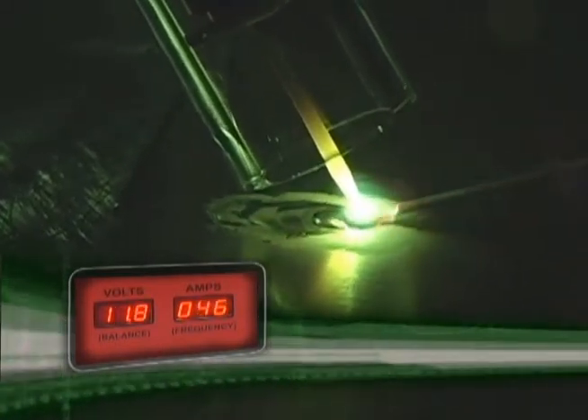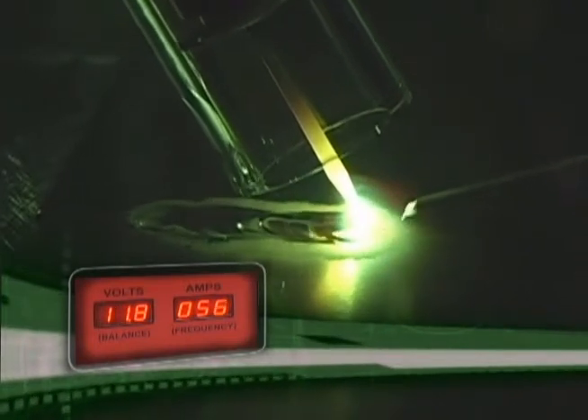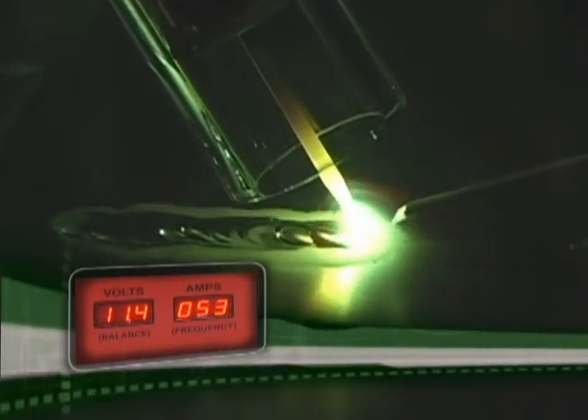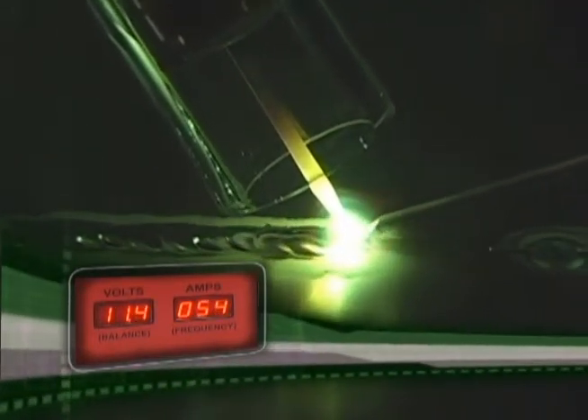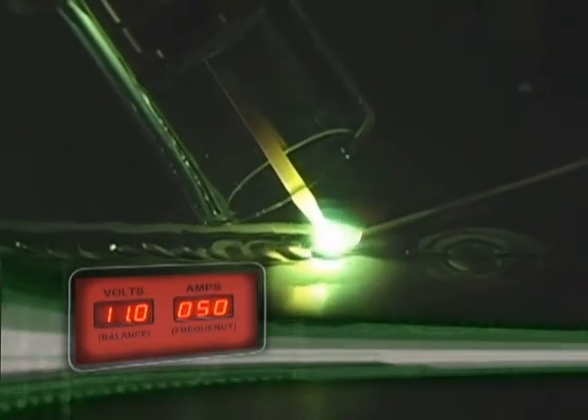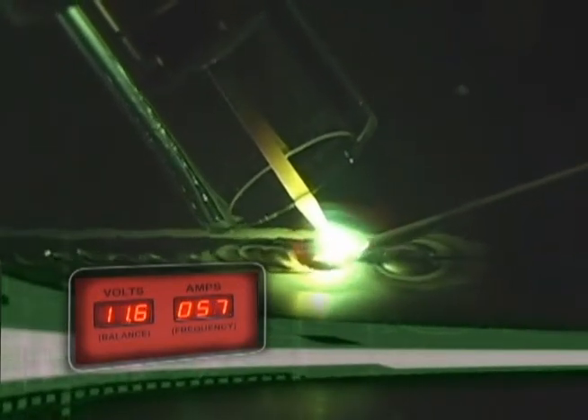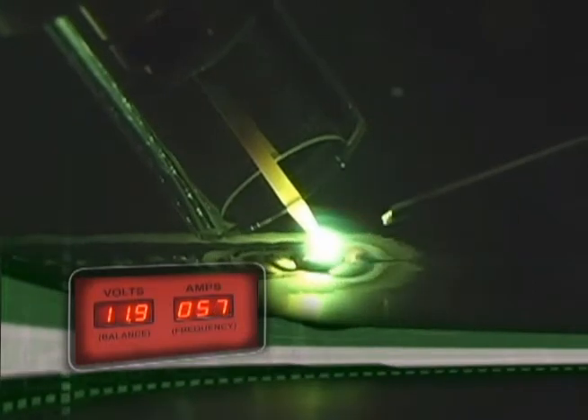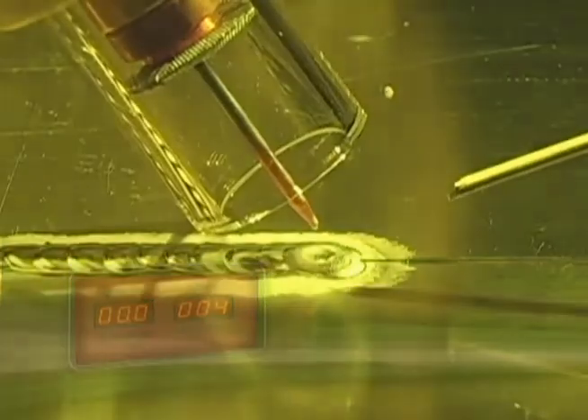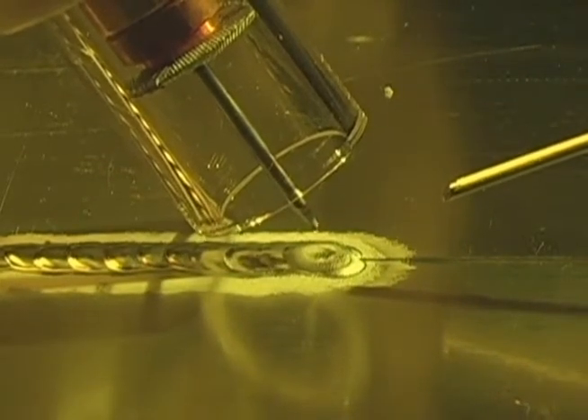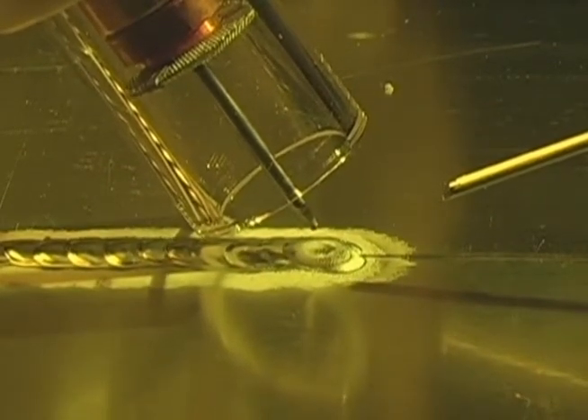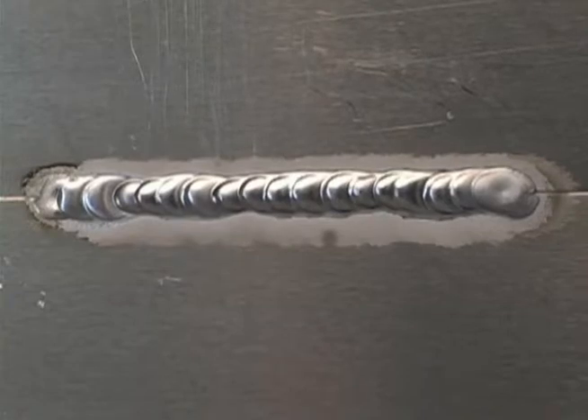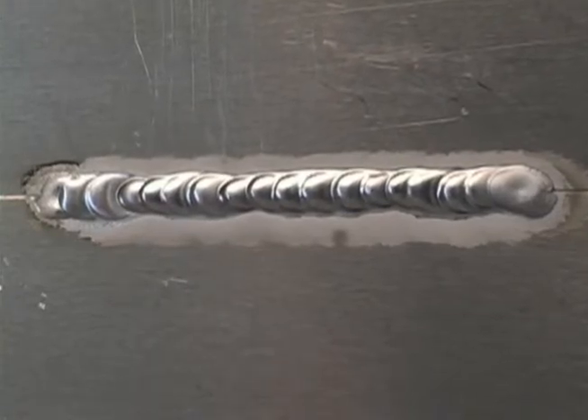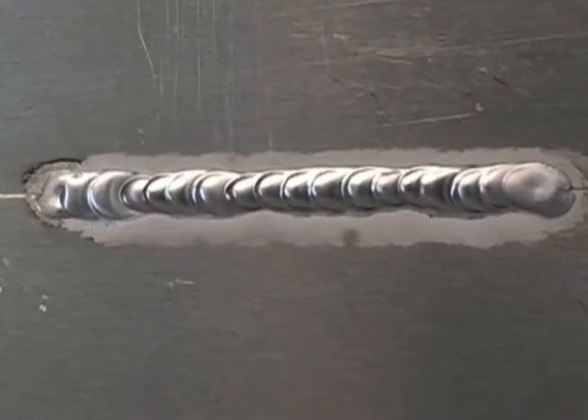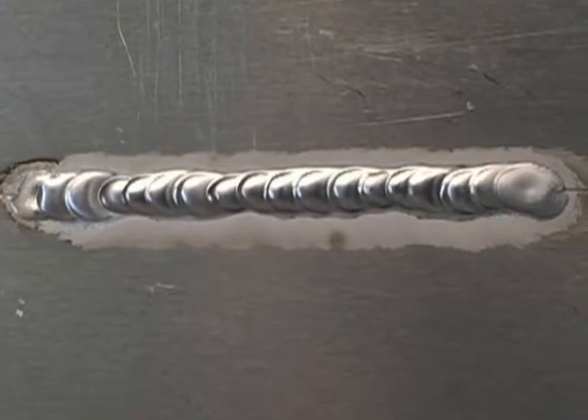Remember, when you are going to end your weld, gradually back off on the pedal. This prevents a crater from forming when the weld pool solidifies. Also, leave the torch in the same position until the post-gas flow stops to keep the flow of argon around the weld until it cools. Here is the finished weld. I'm just a little inconsistent at the beginning, but you can see a pretty nice row of dimes look to the weld.